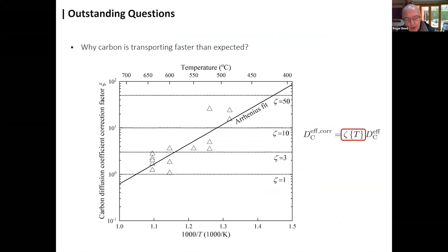Also, of course, we were a bit surprised that carbon is transporting a bit faster than we had expected. Of course, you can criticize the simplicity of some of the modeling. We used the local equilibrium assumption, which of course I had studied long and very hard for my PhD. But of course, these carbides are rich in chromium, but they may not be rich in chromium consistent with the local equilibrium assumption. And certainly we do see in these steels evidence of kinetic retardation and a failure to reach true local equilibrium. So that's probably one of the reasons why this parameter here has to be introduced in an empirical sense.